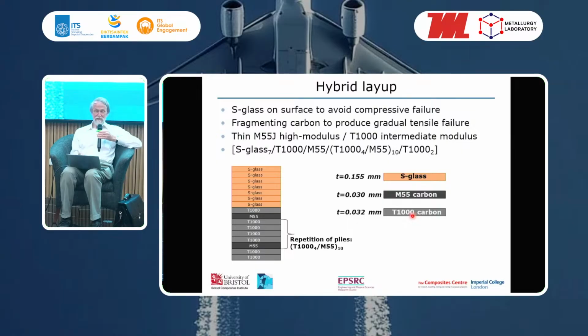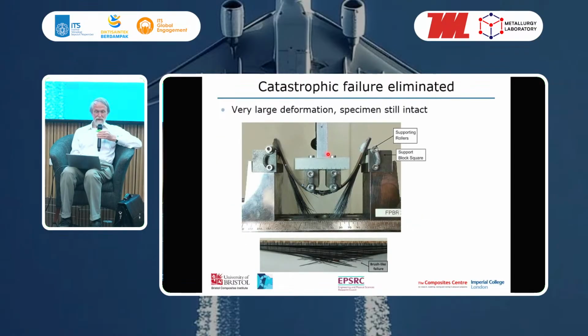And if you look at the specimen under load, it's bent double and actually slipped between the loading rollers, but this specimen is still intact. It's not broken. So these fragments on the tension side are broken off, and when you unload it, it goes back like this. You can see you've still got glass and some carbon which is intact on the surface here, and all these spears of the carbon fibers which have failed on the tension side are just left like a brush type failure. So we got a very gradual response there, and the specimen is unbroken, is intact, and can still carry load if we want to load it up again.